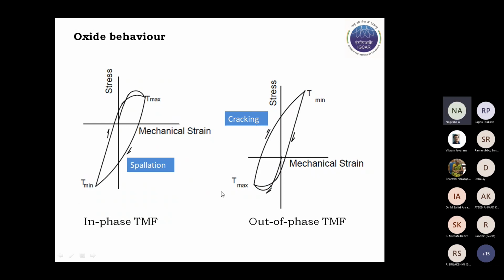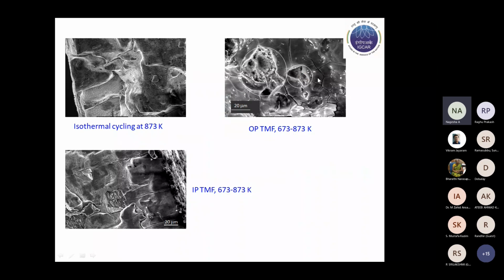In comparison, there is cracking of the oxide layer in the case of out-of-phase cyclic loading, where the oxide forms at the peak temperature at the maximum compressive strain, which on being subjected to tensile strain during the changeover from the compressive to the tensile part, gets cracked widely. So in OP TMF you can see a lot of damage associated with oxide cracking, as against the situations in the isothermal and IP TMF cases.